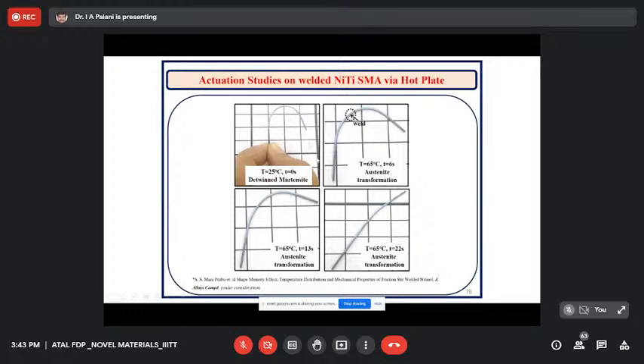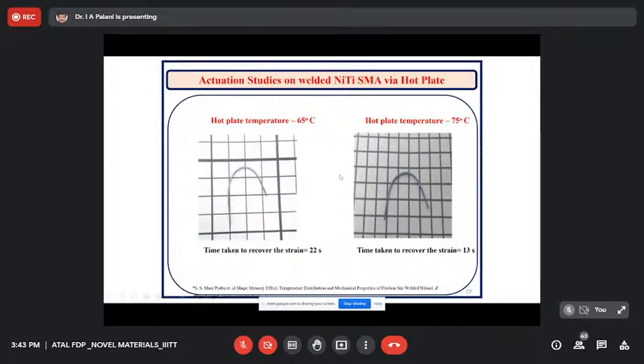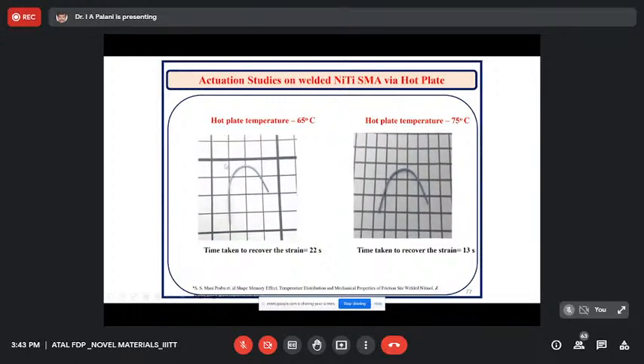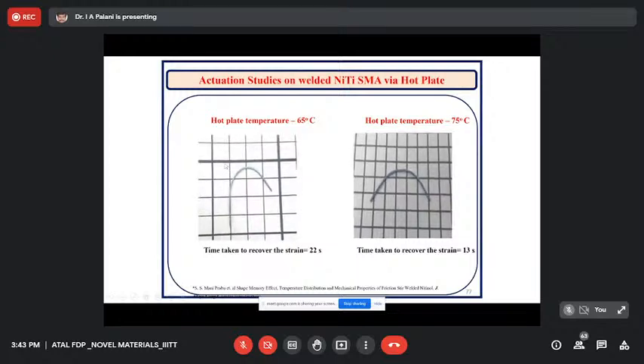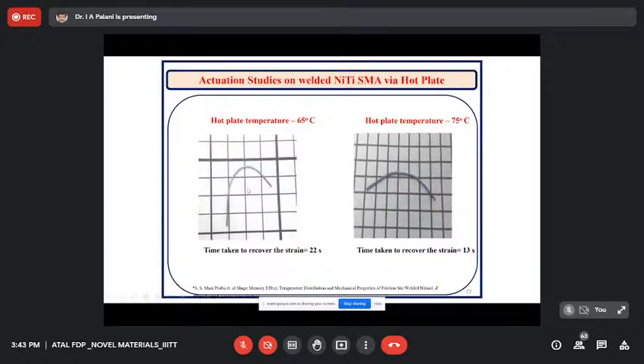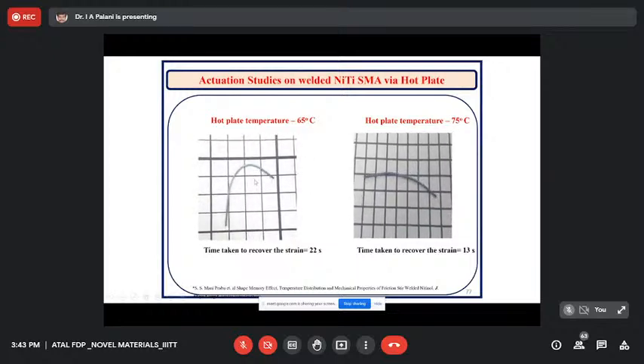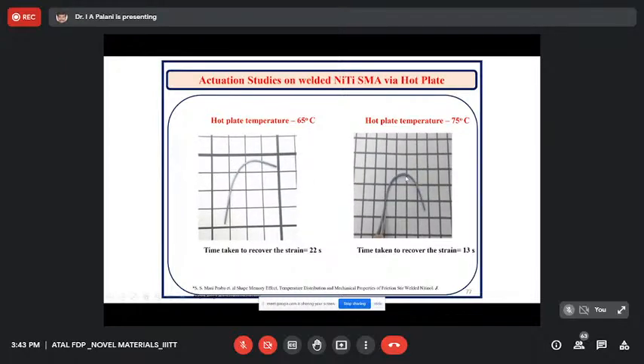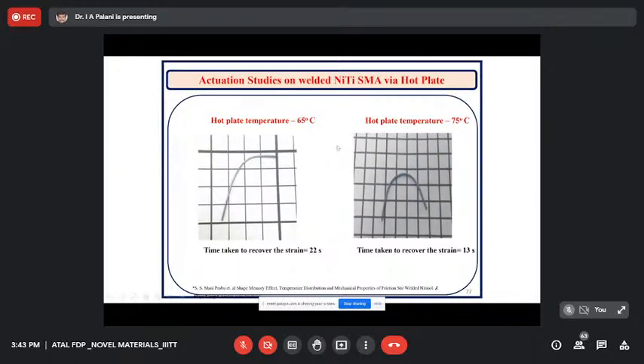This is initially in the low temperature phase, and when we apply a temperature of around 65 degrees Celsius, there is an elongation happening. This is exactly the weld point, where, if you see, there is no breakage happening on the surface. I think I have a small video about it. This is a hot plate study. At 65 degrees Celsius you could see a very small response, and at 75 degrees Celsius we could get a higher response.